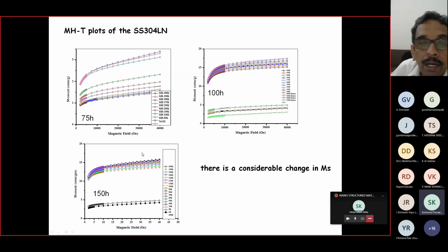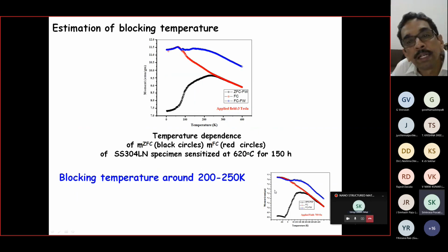It is varying, and you can see that as I vary the temperature, the saturation magnetization is changing. From this, if I plot the individual magnetic moments at different temperatures, I can get the temperature at which this transition is occurring in the saturation magnetization. This is what I try to understand, and from this we could estimate what is known as the blocking temperature.